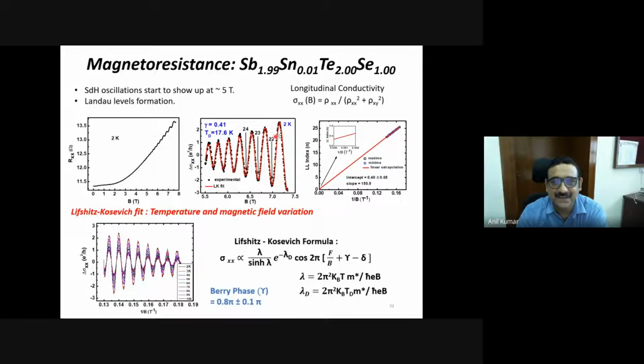Not only that it has got an oscillation, so those who are working in this area will know that we have Landau levels in this sample. So you can plot this Landau level index like 22, 23, 24, 25, 26, 27 like that, and plot as a function of 1 by B. Then you get a linear plot, and that linear plot is hitting this intercept at 0.4 plus minus 0.05. 2 times of that is the Berry phase in this material. So this tells me that there is a pi Berry phase in the sample.